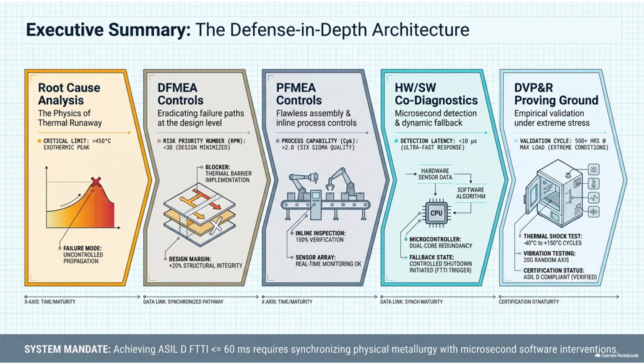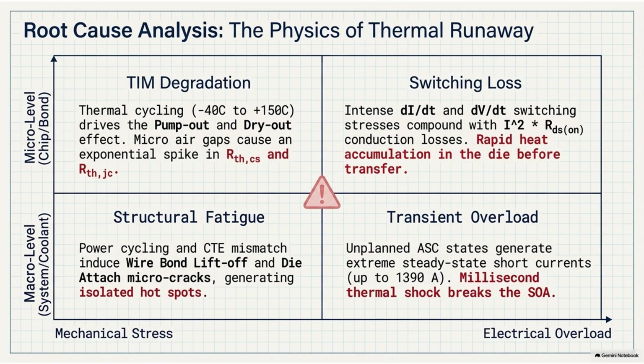And we have to look at how different materials react to that swing. This is the coefficient of thermal expansion, or CTE. Okay. Everything expands when it gets hot and shrinks when it gets cold, but a silicon die expands at a totally different rate than a copper base plate. Right. And that expands at a different rate than the aluminum housing. So it's like a microscopic tug of war? A violent one. Yeah. This constant expanding and shrinking at varying rates across different layers creates intense thermal mechanical stress. It causes the metal plates to literally warp, bowing inward and outward. Which means it is constantly squeezing and releasing the thermal paste trapped between them.